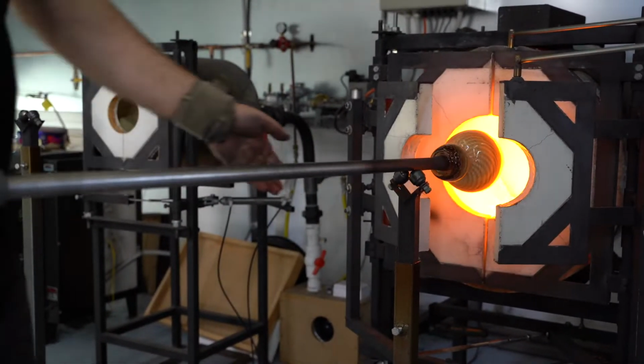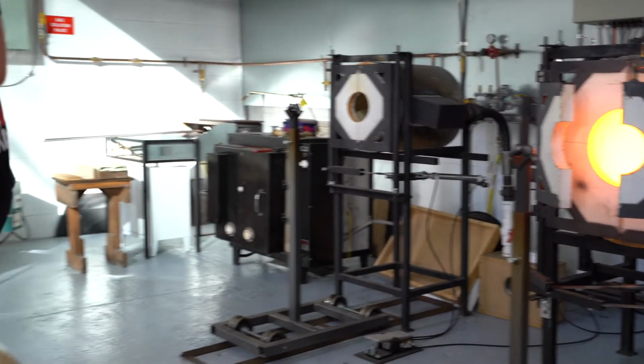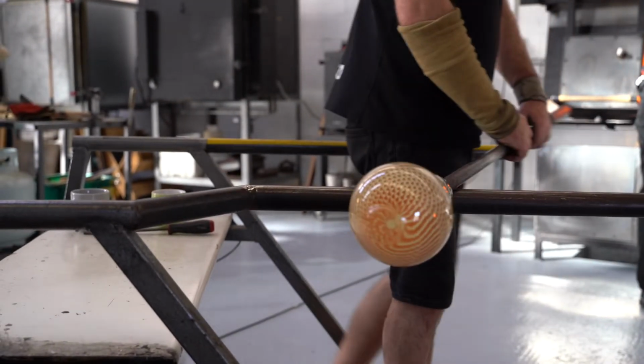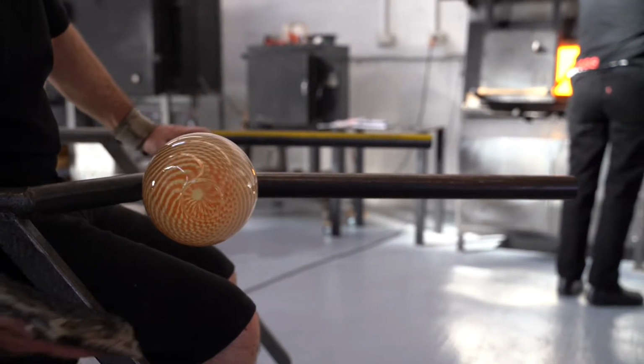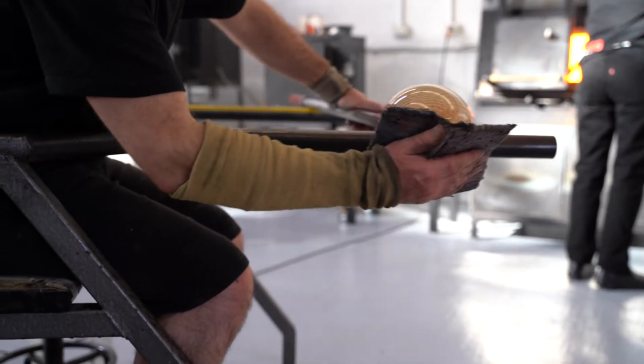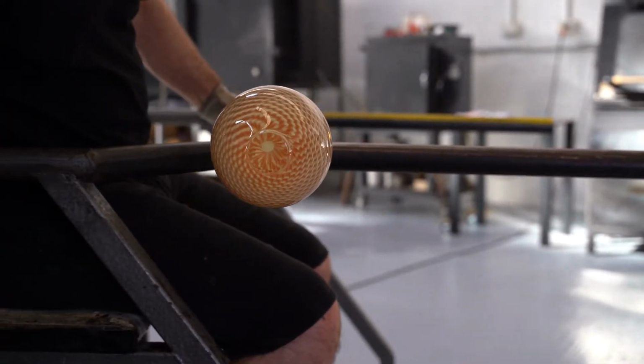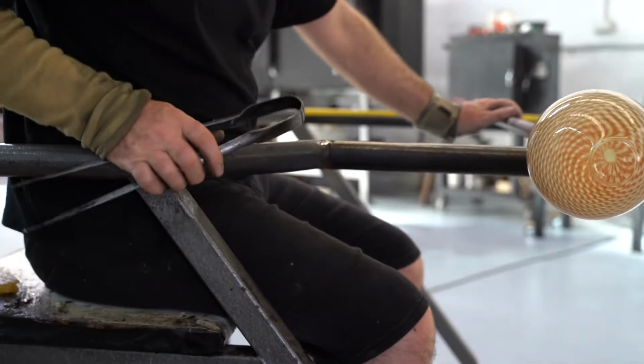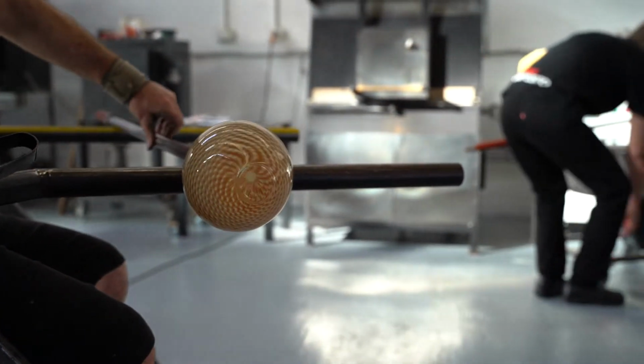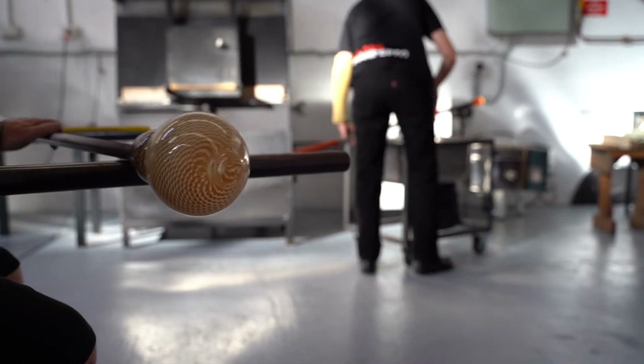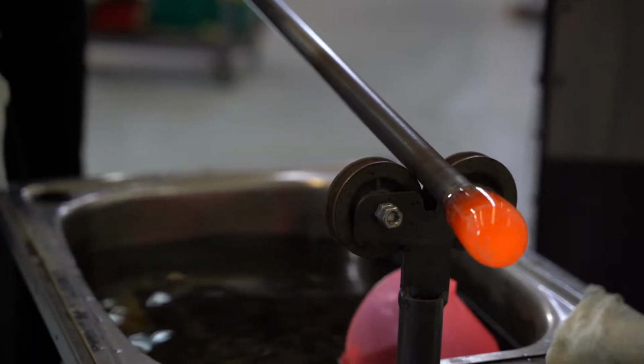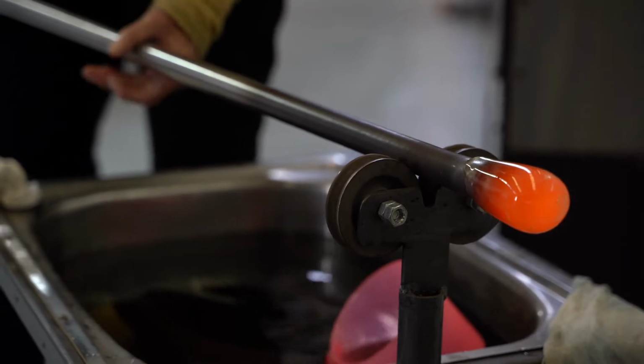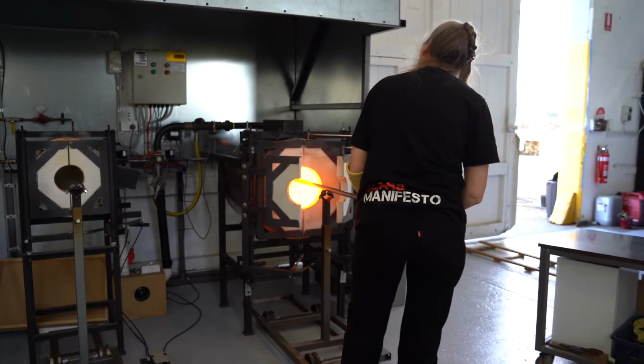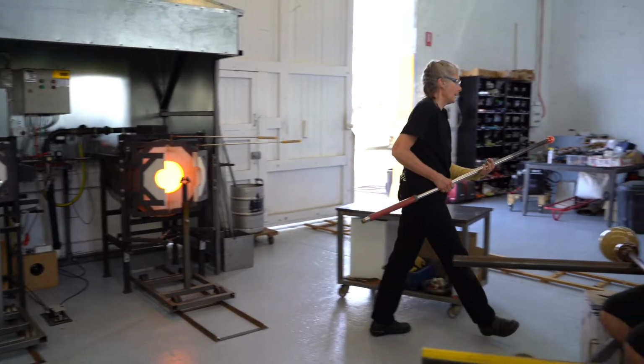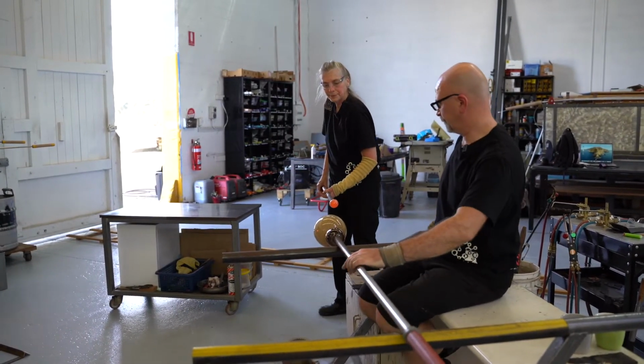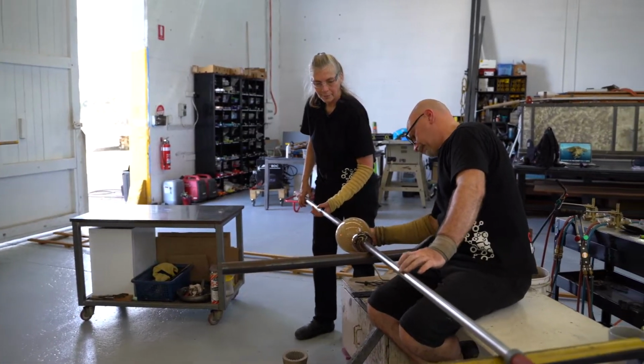The glass, shape it, and then we're going to stick these two things together. So Anne's just starting to prepare a second pipe. We're going to be transferring this piece onto a second iron so we can start to work the piece from the top. So she's taking glass from the furnace, she gives it a particular shape, waits for it to be at a very particular temperature, at around 800 degrees, and then we'll actually be joining Anne's pipe to this prepared flattened pad on the bottom of the piece. And so we're just using the fusibility of glass here, so it's just tack fused as a temporary join onto the bottom, and that restriction that we put in the top is now made as very weak points.